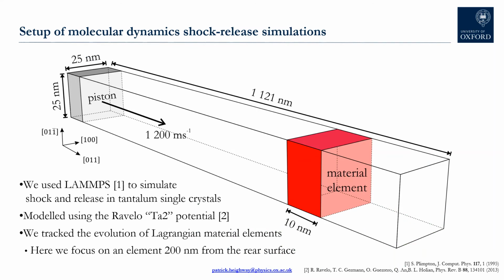So I'll first talk about the molecular dynamic simulations we performed to that end, which were actually very simple in their design. So we simply take single crystals of tantalum with their [011] direction aligned with the loading axis, Z, and shock compress the crystal to about 100 gigapascals using a constant velocity piston. And obviously we run the simulation long enough that the crystals can be allowed to release.